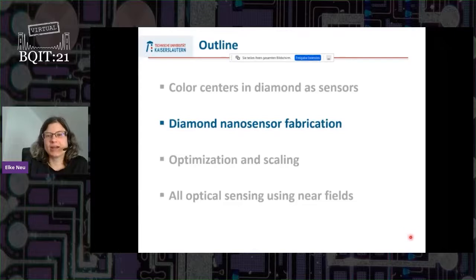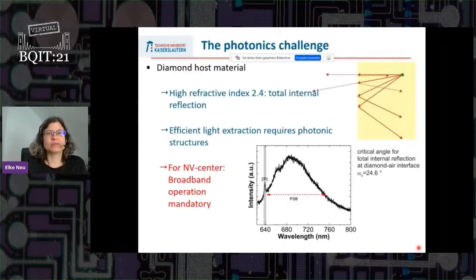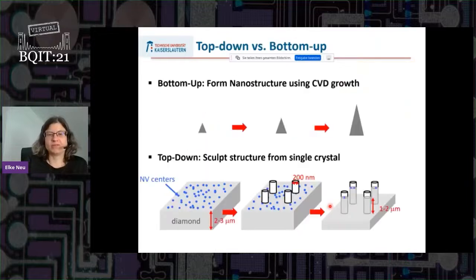Okay, now let me quickly say something about how you can make such a diamond AFM tip and what you have to keep in mind here. First, diamond has a very high refractive index, 2.4. So most of the light of the color center just stays in the diamond because of total internal reflection. And the nitrogen vacancy center has a quite broad emission band, roughly 100 nanometers of emission width. So you want your AFM tip to be a photonic structure that efficiently extracts the light and also works with this broad emission. This is important.